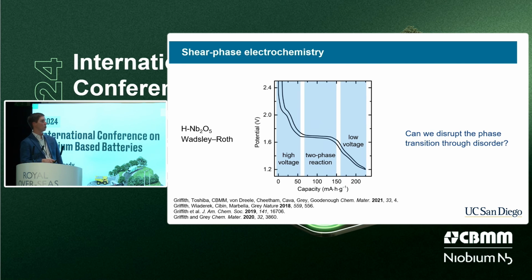Okay, so one important thing at the beginning, and what I'll go through here discussing the structural chemistry of these materials, is that for many years we had a big focus on disrupting this phase transition, because phase transitions are usually associated with a dip in the diffusion coefficient of your transporting ions. Maybe it's an ordered phase, or maybe it has a volume change and a strain associated with it. So it's often helpful to avoid these phase transitions.